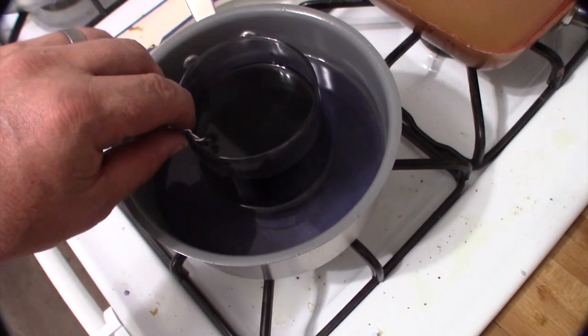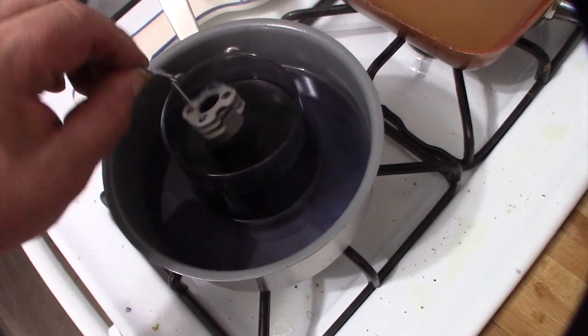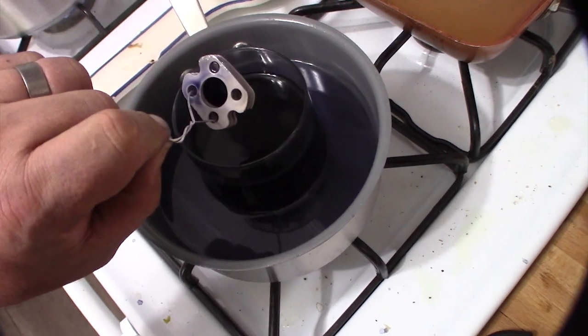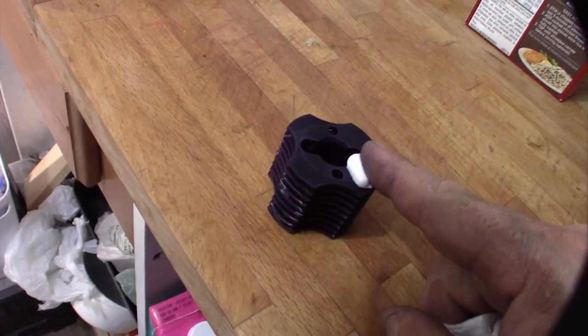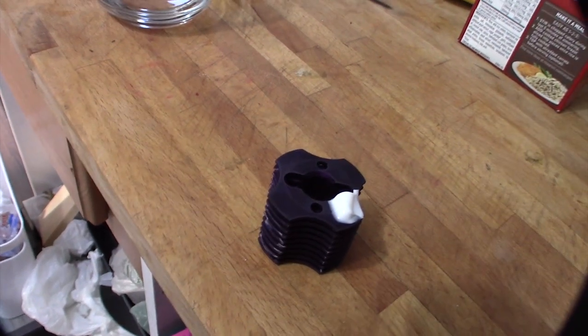Here's an example when you go too aggressive with the amperage. The pores become too big, and the dye doesn't stick, doesn't go into it. So I have to redo this. Alright, so if you get that little roughness, that's toothpaste. It's really kind of abrasive. Rub that in. See if I can polish it up.